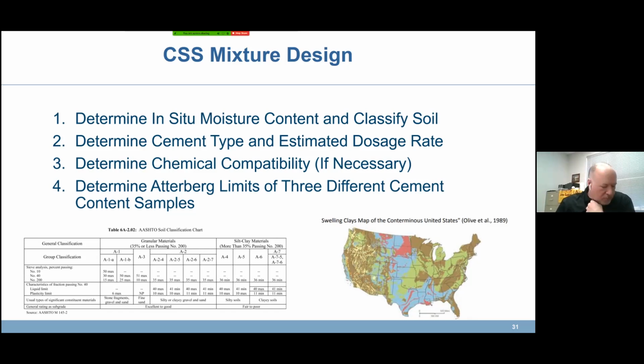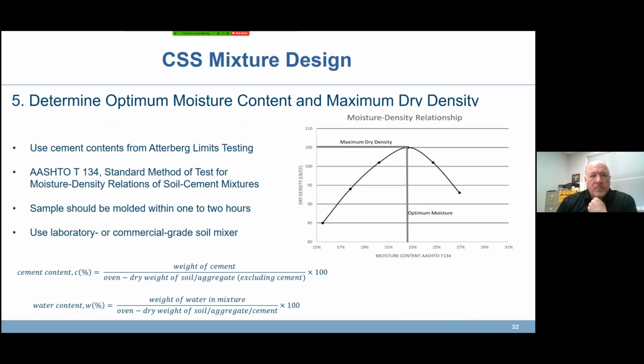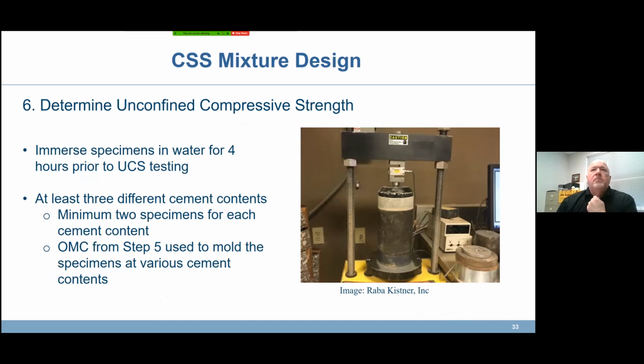Are these similar to the cement treated permeable base that we are starting to use? That question came in about 5 or 6 minutes ago, so I'm not sure which slide that is in reference to. But I will say in Michigan, again, we take our existing concrete, crush and reuse as a base material. On some projects, instead of using it as an unbound recycled concrete base, we're using it with primarily cement as a binder, more to tie up the chips and the dust that we're trying to screen off, but some of that stays in and creates some leachate, some calcium carbonate, which can potentially plug up geosynthetics, separator fabrics, as well as potentially the sub-drainage systems, underdrains and outlets and things like that. So I'm not sure which one you had in there, but yes, cement treated permeable base.